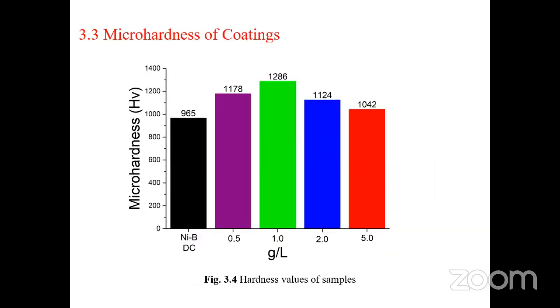Microhardness of coatings. The figure shows the microhardness values of the nickel boron alloy coating and nanocomposite coatings. Addition of boron carbide to the electrolyte leads to an increase in microhardness, but after a certain point, microhardness values decrease because the over-addition results in agglomeration. The hardness value was measured at approximately 1,286 Vickers hardness for 1 gram per liter addition of boron carbide, and the lowest hardness value, which is 965 Vickers hardness, for the nickel boron alloy coating produced by direct current.